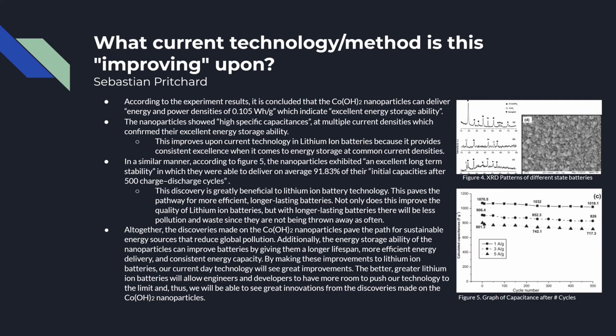So what current technology method is this improving upon? So according to experiment results, it concluded that the cobalt hydroxide nanoparticles deliver energy and power densities, which indicate its excellent energy storage ability. The nanoparticles showed high specific capacitances at multiple current densities, so that further confirms their excellent energy storage ability. So what does this mean? This improves upon current technology in lithium-ion batteries because it provides consistent excellence when it comes to energy storage at common current densities.